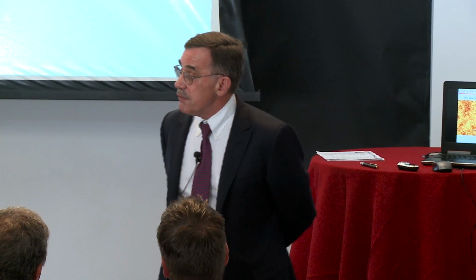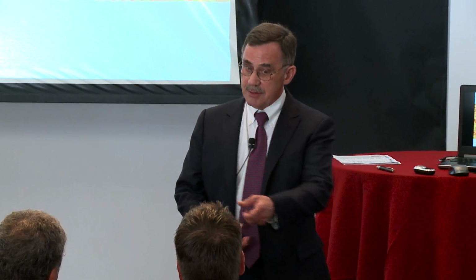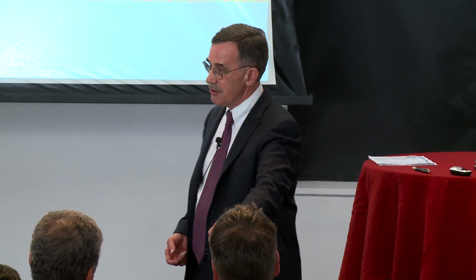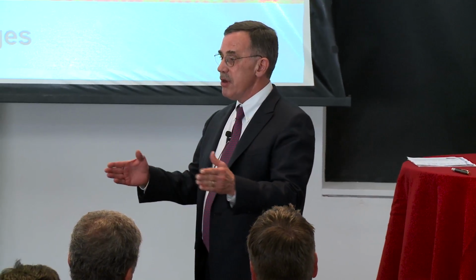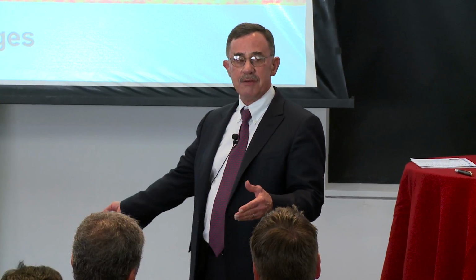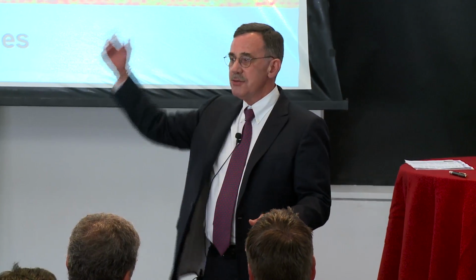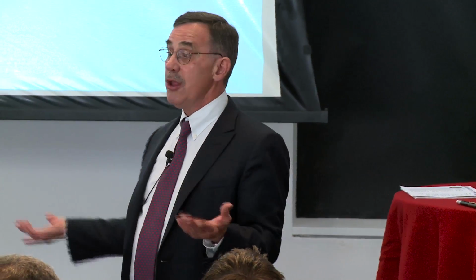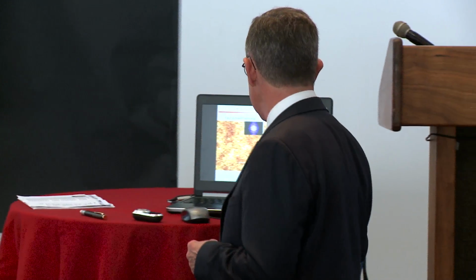If we remove the solvent slowly, then the less solvent, Curtis and I get to dislike each other and want to separate. So the separation distance starts to increase. I can't fall off the side of the substrate, so I have to do something with this extra material. I have to put it somewhere, and the only place it can go is up. No other way. So I'm trying to compensate for this lateral frustration I'm putting in the film by effectively increasing the overall thickness of the film itself.